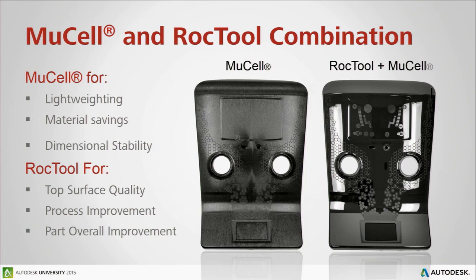So that part right here is conventionally molded with the MuCell, where with laser texture details, we have a high gloss zone, we have a big weld line in the middle, we have a little square of super thin wall, less than 1 millimeter here, and then low gloss on the top and the bottom. And you can see the mess because all that MuCell, little bubbles of gas mixed up with the resin, get on the part. It would be the same thing with fiber. And then as we turn on the temperature, we bury it a little bit like a sandwich structure. And then you only have that nice PC/ABS on the surface that reveals all the details.